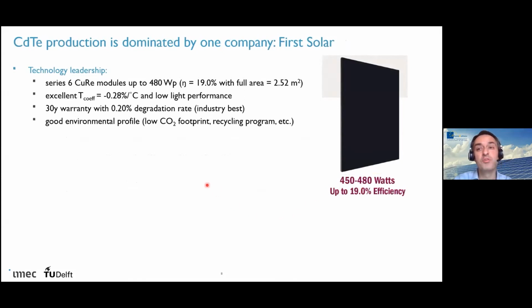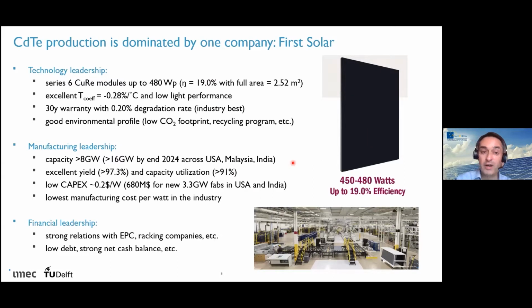So if you look at the cadmium telluride, we can basically say that the 6 gigawatt is produced mostly by one company. It's the company called First Solar. It's an American company, and they really have the technology leadership in this technology. So they have been able to make very large, 2.5 square meter panels with 19% efficiency. So that is around 500 watts that one panel is giving. And these are very robust and stable PV panels. And they are now manufactured in quite large capacity. So they have a capacity of 8 gigawatts, and they are expanding to 16 gigawatt in the future.